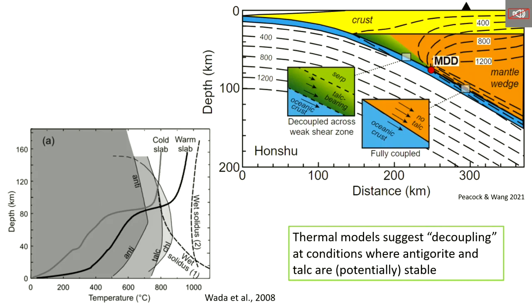All right, now Hannah gets to be the star of the show. So talc, everyone knows talc is weak. But one of the other weird things about talc is all the experiments that have been done on it have shown brittle deformation. And no one had ever really tried to deform talc at high pressures before. And by high, I mean like a gigapascal or 2 gigapascals.